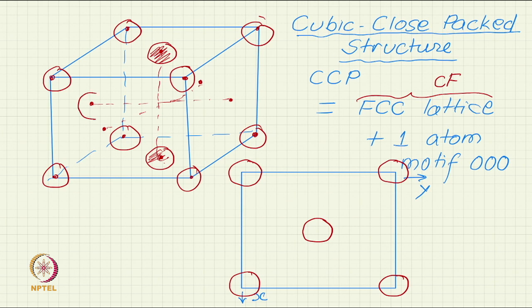Now, let us look at the left face center, where will that project? At the left edge. So, it will project exactly there, and its height is half. Since we have decided to indicate the z height, because that cannot be read from the projection, unless somebody tells me that it is at half height or is at the same plane or at 3/4 height, I cannot know. There is no way of knowing, whereas x and y coordinates I can read, as I told you. So, that is why there is this convention that the z coordinates are always indicated.